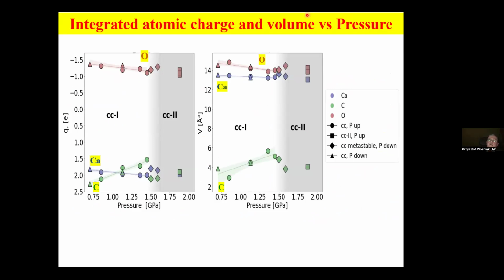We can get integrated properties such as charge or volume, and as we can see here, the charge of oxygen atoms is decreasing with pressure. We have a kind of metastable phase before we are getting calcite 2 to form. We can see that the carbon atom is getting charge. The positive charge is decreasing with increasing pressure, and calcium is giving up charge. And again, a clear manifestation of this metastable phase.